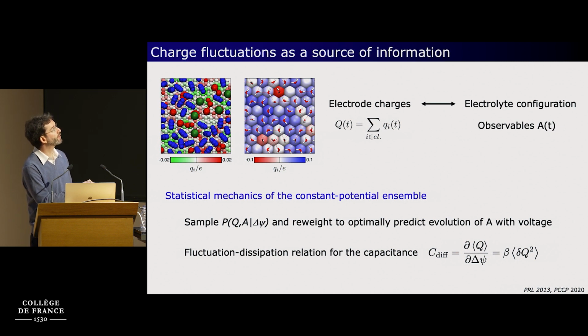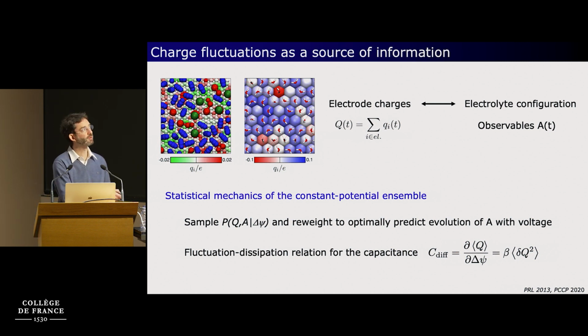And for example, you can see that the local charge below each water molecule depends on the local orientation. So here you have water molecules with an OH bond pointing towards the surface, and the local charge is negative, whereas below the water molecules that lie flat on the surface, because they are involved in a hydrogen bond network with other molecules, then the local charge below the water molecule is slightly positive. And so the electrode charge, the individual one, but also the total charge of the electrode is correlated with electrolyte configurations and probably with all the observables that you can compute. So any observable that is related to the configuration of your electrolyte, that could be density profiles, molecular orientations, number of adsorbed ions, and so on.